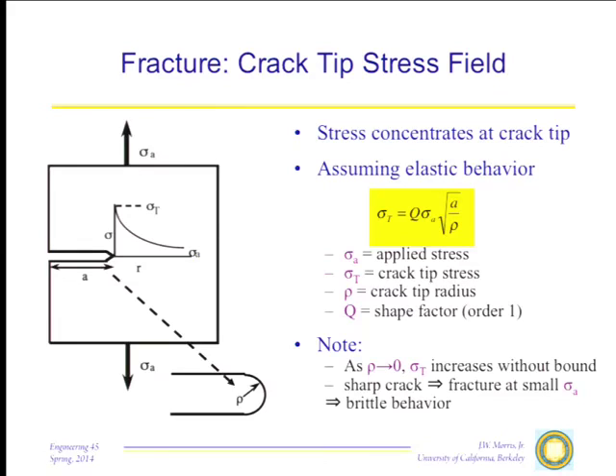So you take a brittle material. Well, for example, how do you cut glass if you're going to shape a pane for a window? You don't take a saw to it, you just shatter the glass. You take a little scribe, you run it over the surface, and you take the glass and just tap it, and it breaks right there. What that little scribe did was it put in some cracks. Not very big, but glass is a material with a very high yield strength. So you get a sharp crack in a piece of glass and you load it up by tapping it. And even though the load you put on it may not be very high, the load here at the tip of that crack is huge. And so boom, there it goes, it pops. And that's basically what fracture is all about, and it's amazing it took them as long as it did to figure that out, but they did.